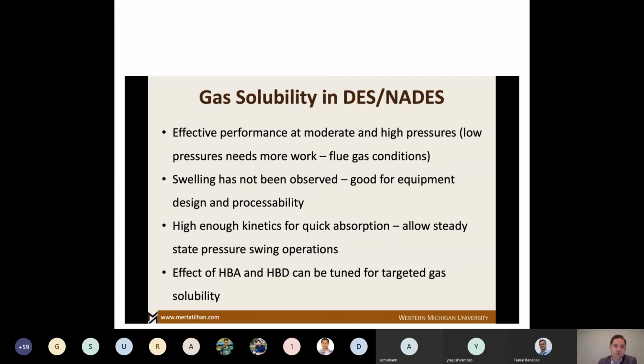We have observed that low pressures might need work, especially at flue gas conditions. We have been considering adding some synergetic materials to our deep eutectic solvents. Water content might be one issue. In the case of water content, yes, you will be increasing the gas solubility performance even at low pressures, but then you're going to introduce another problem, such as the desorption of the absorbed gas. So that might lead to, again, an energy intensification issue.